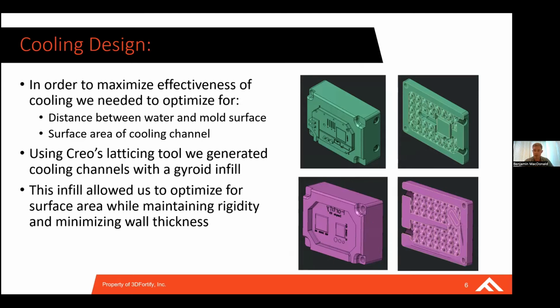The lattice cooling channel enables structural support due to the nature of a lattice geometry. What it also enables is a lot of surface area inside of that cooling channel. If we look at our heat transfer equations, we can easily see that with a constant thermal conductivity, we have two real parameters we can pull on. That's the distance from the mold surface to the cooling channel, and then the surface area of the cooling channel itself. Optimizing for both of those parameters enables us to really maximize the cooling benefits that we might be able to see.